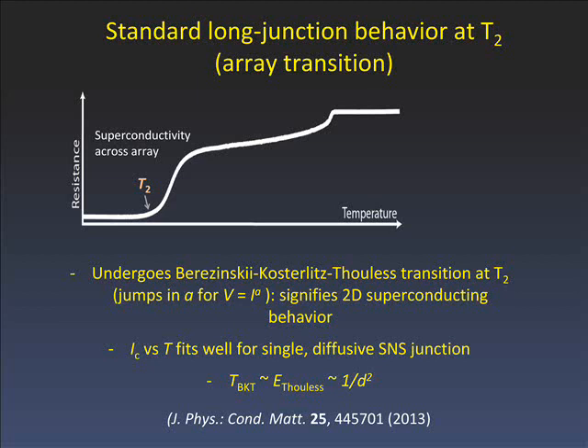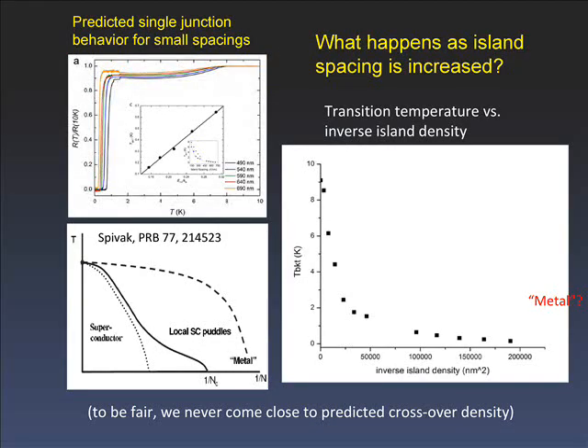The second transition really acts like a standard 2D superconducting transition — it acts like a BKT transition. We see things like jumps in our IV curves, which really signifies it behaves like a 2D superconductor. Below this transition we can really study the behavior of a 2D superconductor in a very configurable system. The critical current fits well as for a single diffusive junction, and we're in the long junction limit where the transition temperature goes as 1 over D squared.